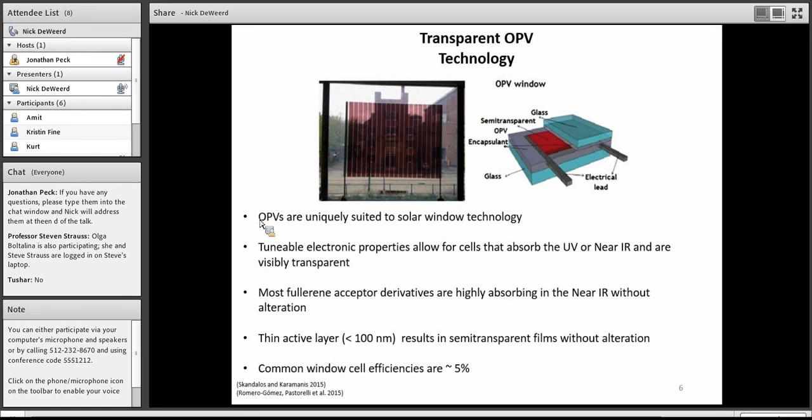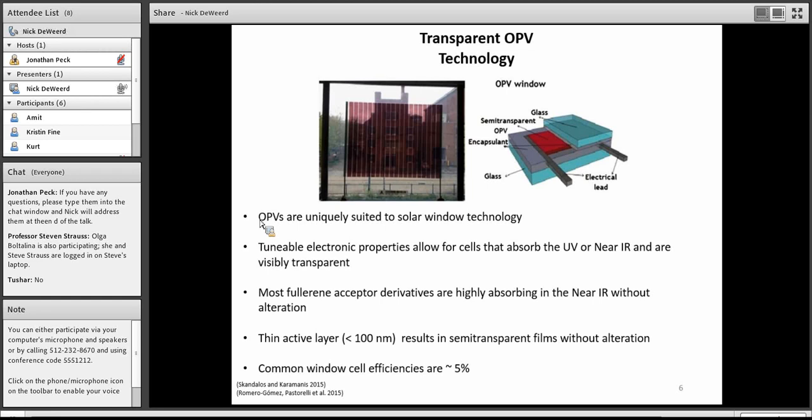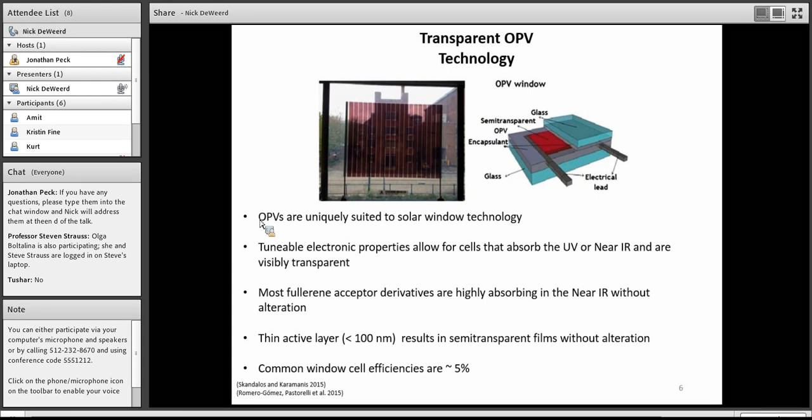With very thin active layers, as I said before, less than 100 nanometers, they're already fairly transparent. So this is a particular application where you can see that the tunability and flexibility of OPV technology can really thrive. However, traditionally, the efficiencies of these types of devices have only been about five percent. There are some outliers where you get some devices that are as high as seven, but the majority of those devices, with good transparency, are only about five percent. You can keep that in mind when we get towards the end of the presentation, and I'll show you some figures from Next Energy.